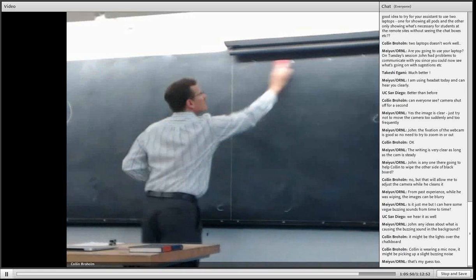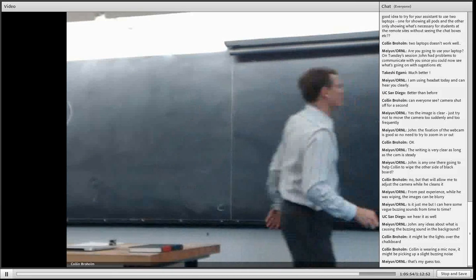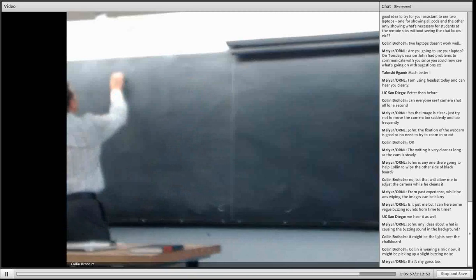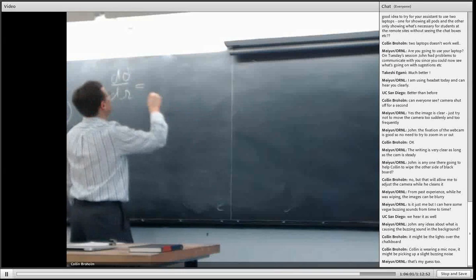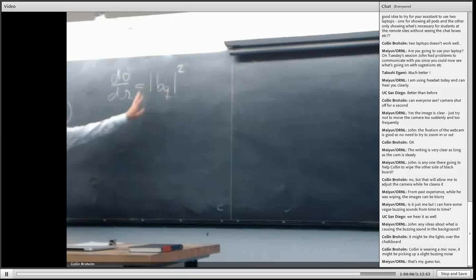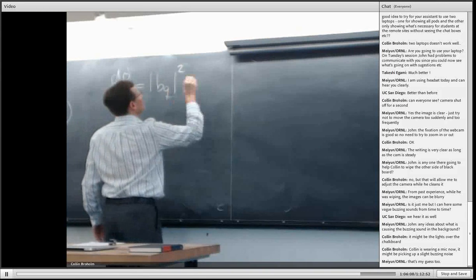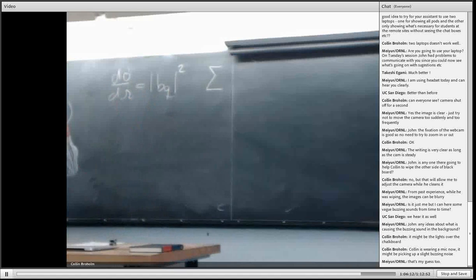So what's going to happen then is that my wonderful expression for the scattering cross section, d sigma d omega, I'm going to repeat it here. It has my unit cell Fourier transform, if you will, multiplied by a set of Dirac delta functions, because only when Q matches these reciprocal lattice vectors will I have a finite value, and whenever I'm not at those places, then I have 0.